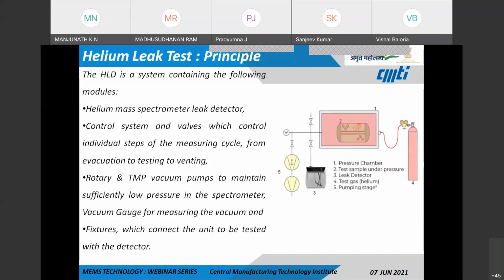So helium leak detection contains the following modules: the mass spectrometer for the leak detector, the control systems and the valves which control the individual steps of the measuring cycle from evacuation to the testing vents, and the rotary pumps and the turbomolecular pumps. These turbomolecular pumps are used because if the packaging is carried out at almost 10 power minus 6 millibar in an E-beam welding chamber, these pumps should be capable of reaching much lower vacuum levels like 10 power minus 11, so that it will create a positive pressure within the package so that the leaks can be tested.